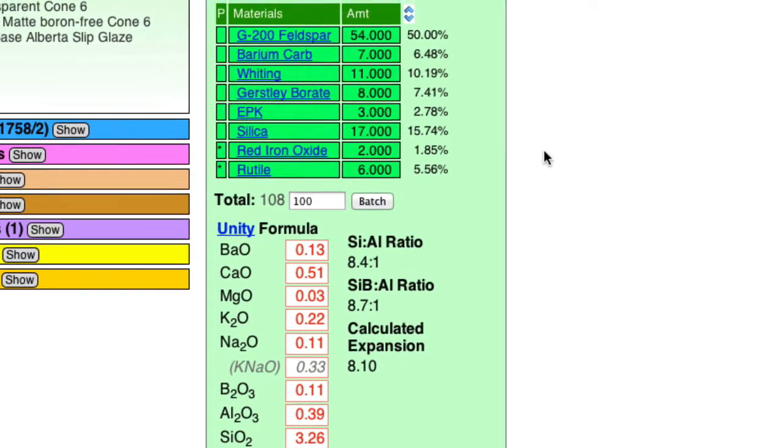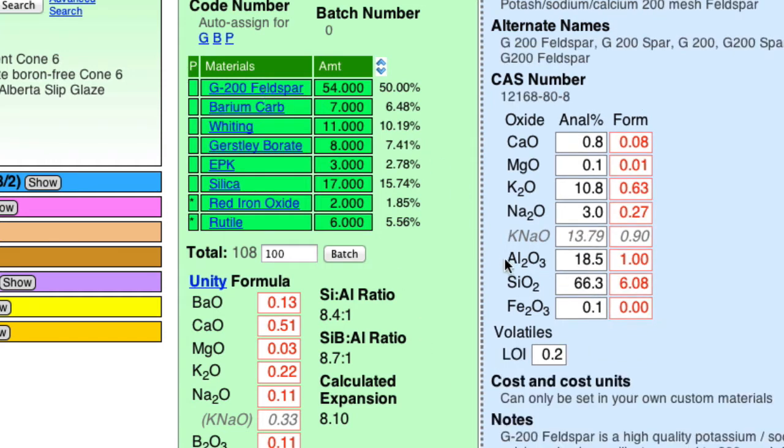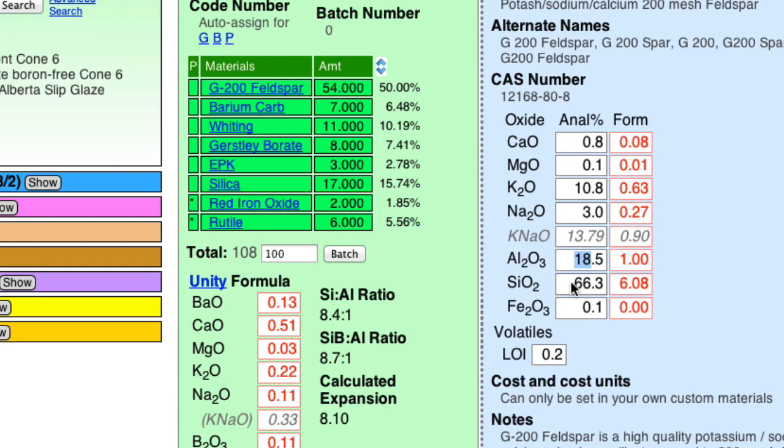It supplies a lot of AL2O3, 37%. And the major contributor of that right now is feldspar. It has 18%. So I need to reduce the feldspar to make room for the kaolin. And that's going to reduce the K-N-A-O. So I'm going to need to supply it from something low in alumina, AL2O3, to retain room for the kaolin. And high K-N-A-O to replace what is being lost from the feldspar. Everything hinges on that.